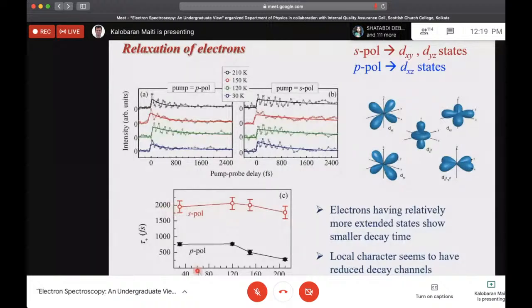And if you use another polarization, you can excite other electrons. Like here you have DXZ and DYZ electrons we excite selectively. It has a lifetime of the order of 600 femtosecond. But if you excite DXY electrons by using a suitably chosen polarization, then it has a much longer lifetime. So from that, you can actually tell which electrons take part in what kind of properties of a system.